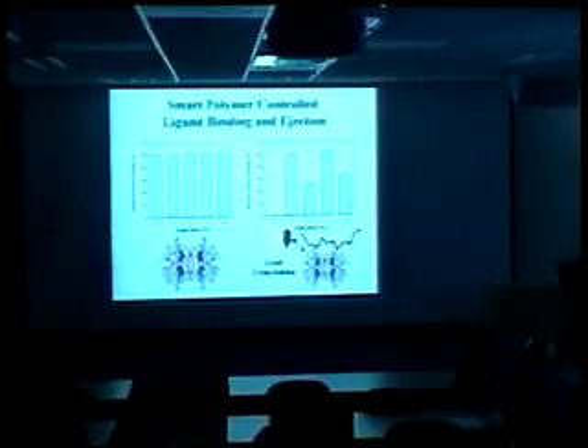And so this is a control where we just look at biotin, the amount of biotin bound on the y-axis as a function of temperature, so you're going between the expanded and collapsed state of this polymer. And the control just tells you that there is no temperature dependence of biotin binding, and that's the problem. There's no reversibility to this binding. On the other hand, with this pendant polymer, we can at least begin to see some release. When we collapse the polymer, we lose about 50% of the bound biotin, and this can be cycled so that eventually, if you go through many cycles, you can get rid of all the bound biotin.